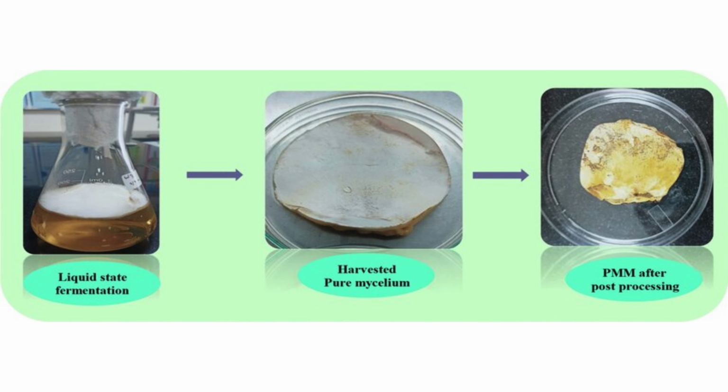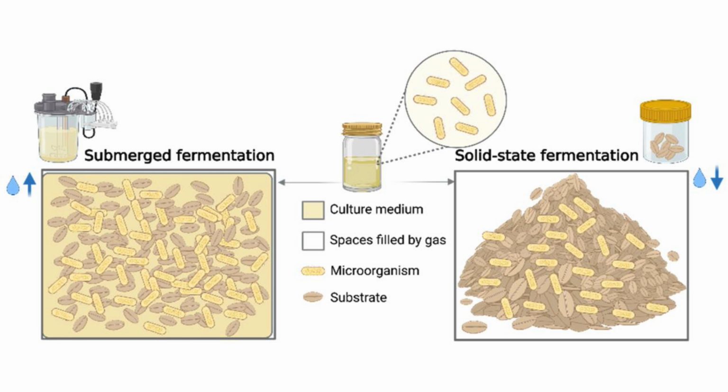Similar to SSF, utilizing LSF is also effective for producing pure mycelial mats. It is believed that this approach of mycelial cultivation also gives room for tunability of the material properties of the mycelium. According to researchers, the material properties of biomass can be enhanced by the addition of porous materials, such as linen or cotton, on top of the surface, allowing the mat to penetrate the layer. Variations of this method have been demonstrated in the works of different research groups. However, the major limitation identified with this cultivation method is the poor availability of dissolved oxygen within the static liquid medium, which affects biomass proliferation.